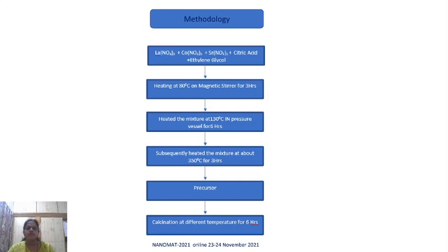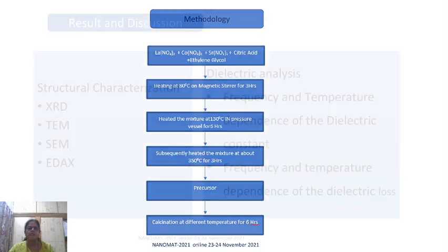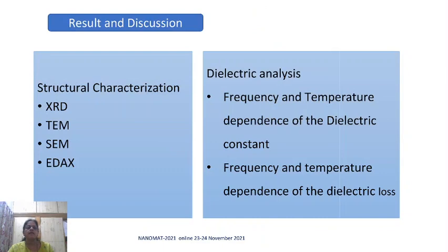The gel was then heated in a muffle furnace at 350 degrees Celsius for 3 hours such that a fine powder was obtained. The fine powder was then calcined at different temperatures for 6 hours. The sample powder was further characterized for structural characterization and electrical properties.